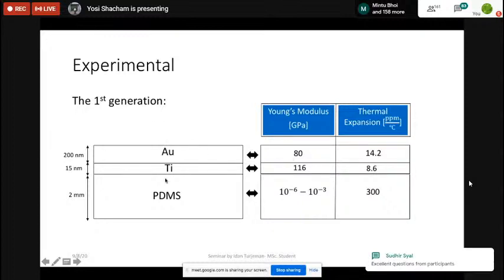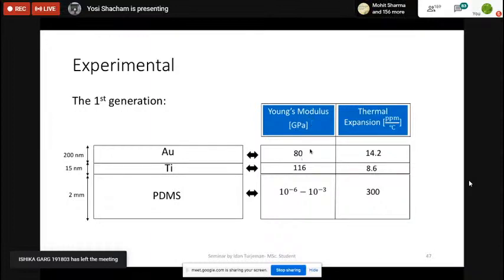The first generation: this is the structure, gold on titanium and PDMS. I'm showing you this to show a very important issue. The materials have different hardness. The Young's modulus of gold is 80 GPa, and thermal expansion is 14.2 ppm per degree Celsius. The PDMS is 10 to the minus 6, 10 to the minus 3. You see a huge mismatch in the Young's modulus, in the mechanical properties. And you can say, this is a very soft material, who cares? Nothing will happen. This is gold, gold is strong, gold is hard.